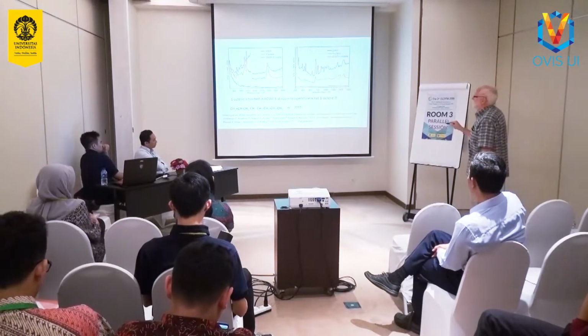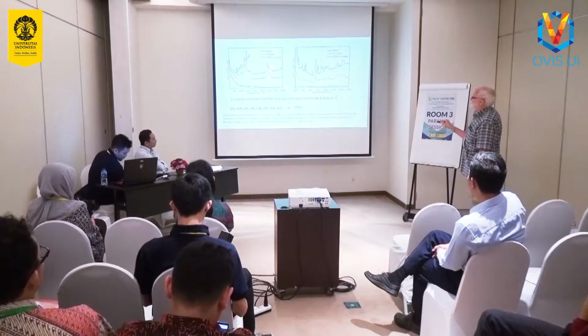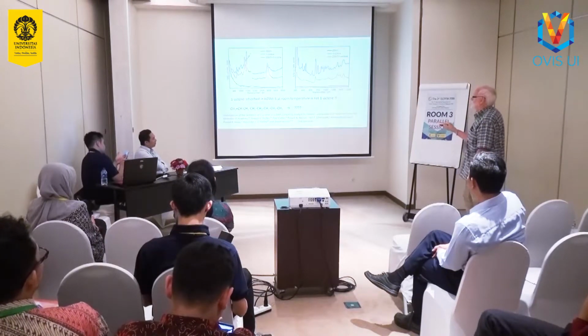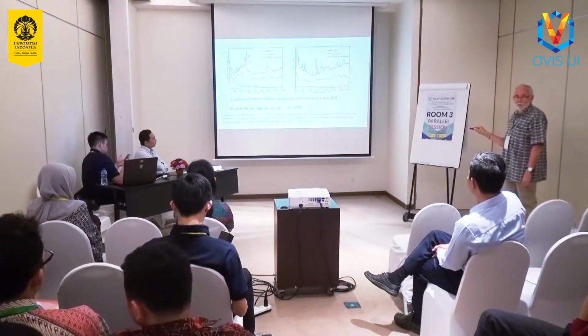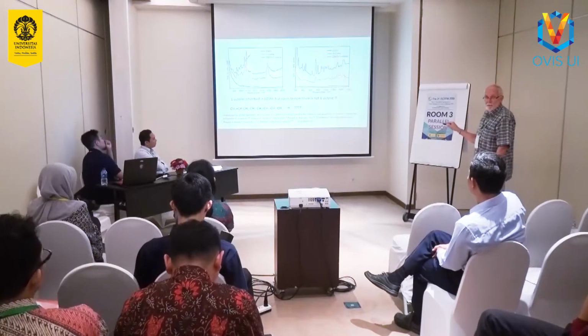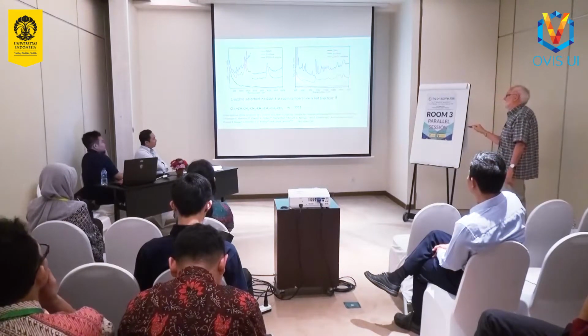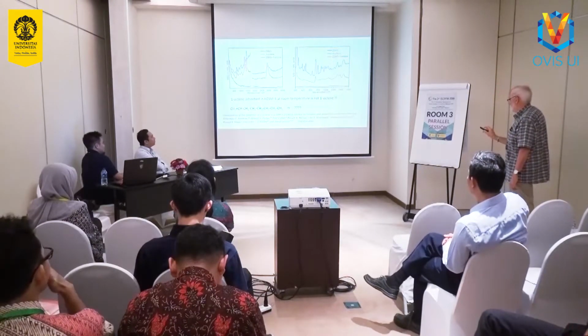Now, you might notice that if we just looked at the CH region, if we were doing infrared spectroscopy on the system, that looks almost the same. We might have just guessed from looking at just the CH stretching region that 1-octene was 1-octene. But when we look at the low frequency, we can see something has happened. Some chemistry has taken place at room temperature, which has changed the nature of what's in the zeolite.